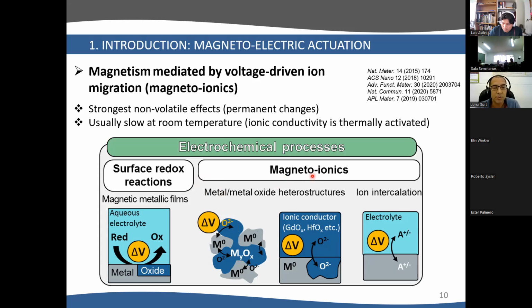But magneto-ionics goes a bit beyond the simple redox reaction. For example, you can have a composite material, particulate or a thin film, coupled with an ionic conductor, and then you can use voltage to induce the motion or the exchange of oxygen ions between the ionic conductor and the metal. And this can be used, for example, to increase or decrease the overall magnetization of the composite or to change the coercivity.